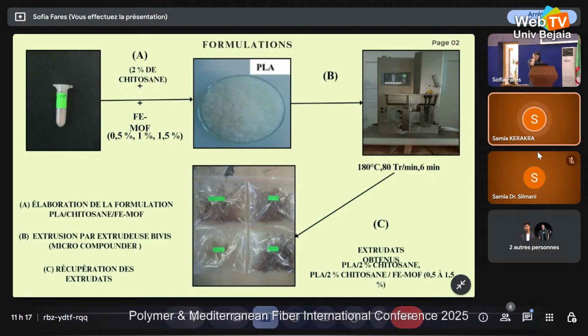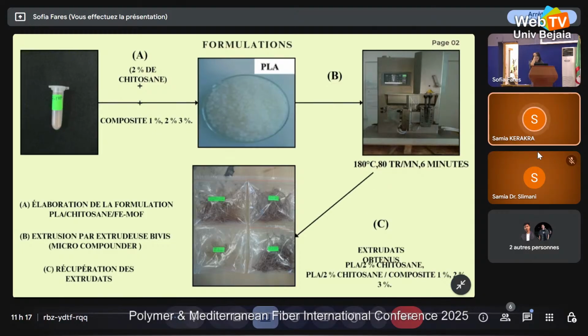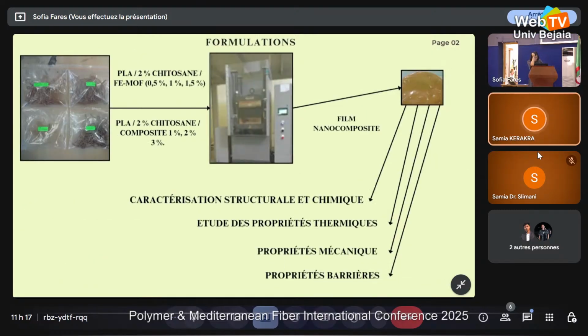It's worth noting that the chitosan used in this study was, prior to use, washed with distilled water, dried at 55 degrees Celsius for 24 hours, and subsequently ground and sieved through a 200 micrometer mesh to obtain uniform particle size suitable for composite preparation. Next, please. Then the extruded materials, PLA and all nanocomposites, were cut into uniform granules and dried to remove residual moisture. These granules were then placed into Teflon-lined molds between metal plates and pressed using a hydraulic press at 180 degrees Celsius. Let's now move to results and discussions.